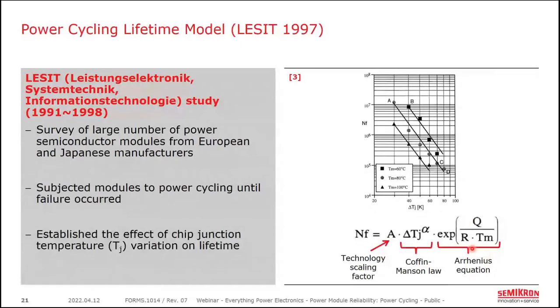And the important thing is that the two main variables that you input here are the junction temperature swing for each cycle. You can see it here as delta TJ, and that mean junction temperature TM shown here. And these other parts are constants or technology factors that you plug in. So the output of this equation is the number of cycles to failure.